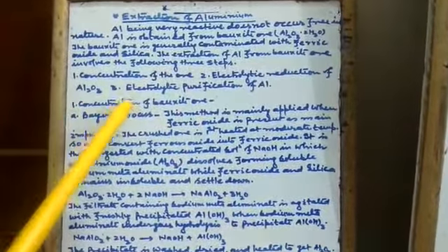First, concentration of bauxite ore. A. Bayer process. This method is mainly applied when ferric oxide is present as main impurity. The crushed ore is first heated at moderate temperature so as to convert ferrous oxide into ferric oxide.